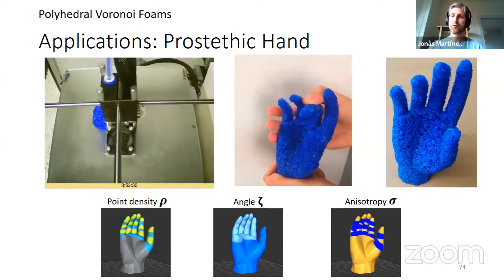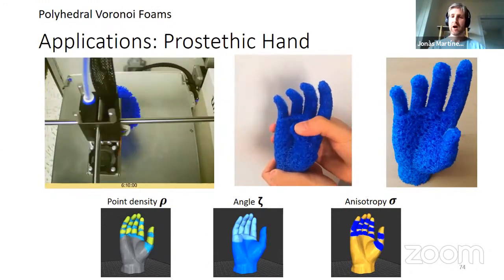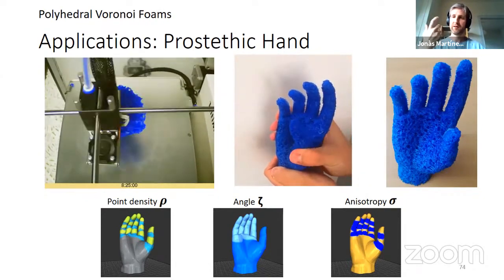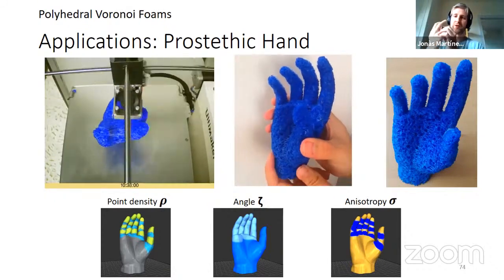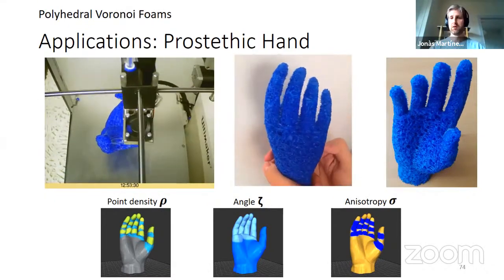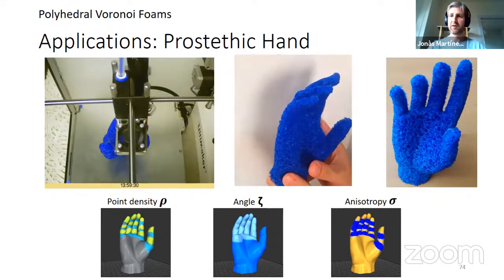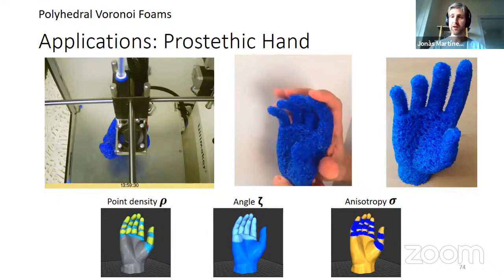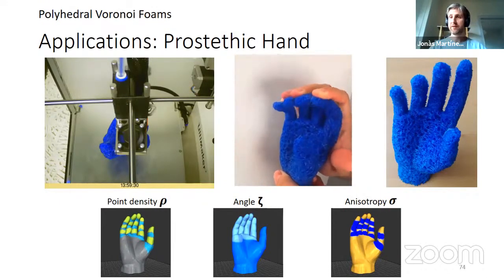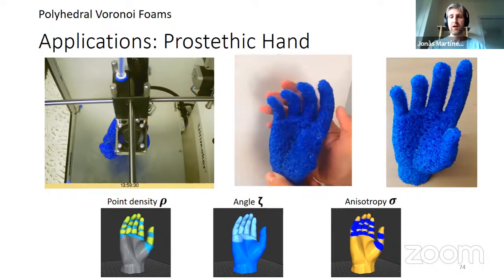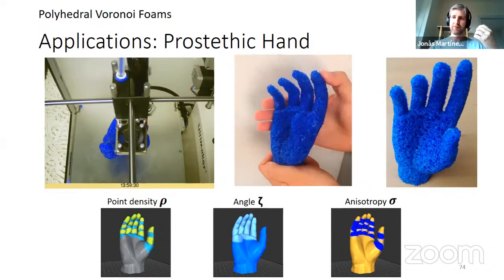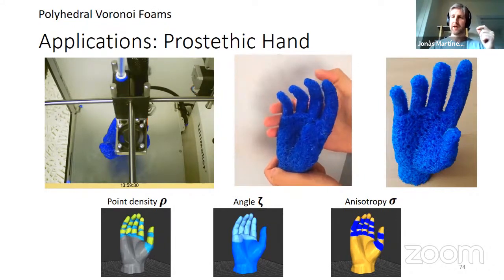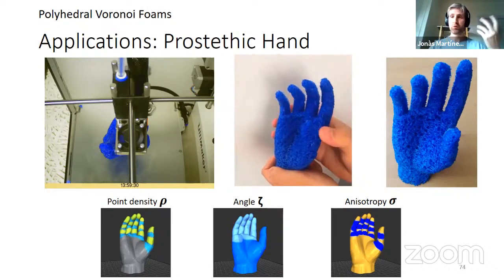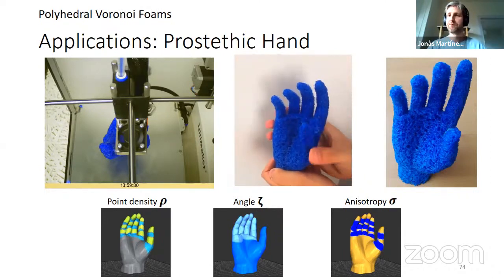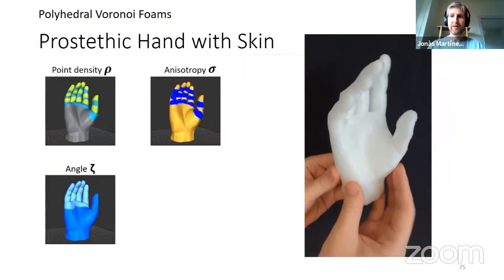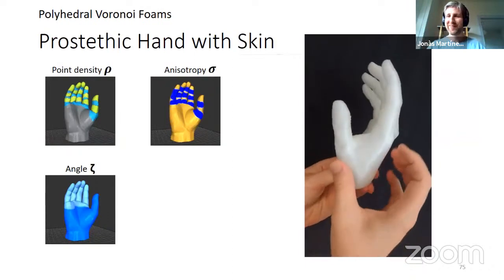It's a prosthetic hand. This was fully printed with a regular Ultimaker. And as you can see, it was articulated by regulating the point density on the articulations and also the degree of anisotropy. What you see is basically the printing. So from our experience, it prints very robustly. What I mean is that you do several prints and you always get a hand. So it's not as delicate as other technologies that from our experience require more fine-tuning. There's a high probability that something goes wrong during printing and you don't get anything. And of course, you can put a skin over it.